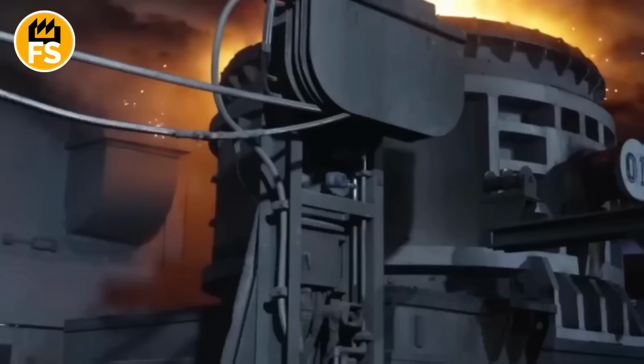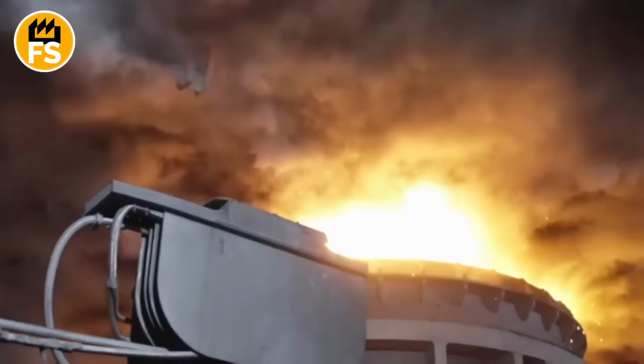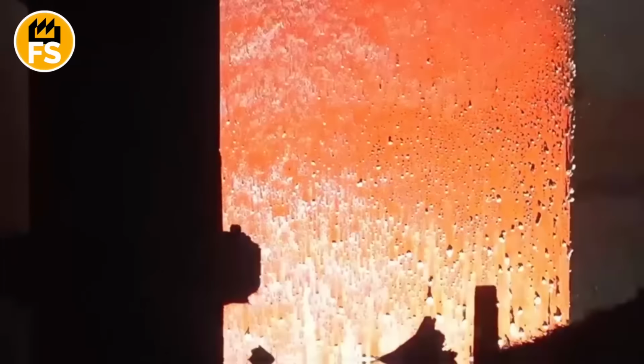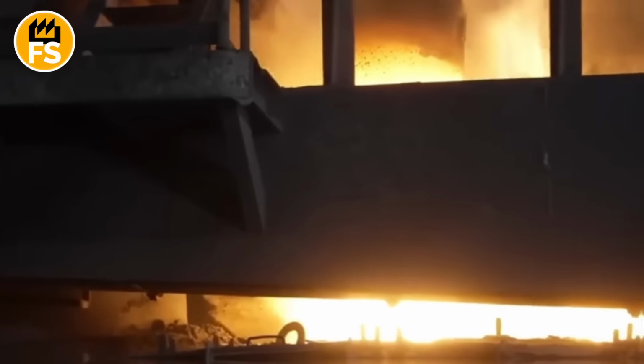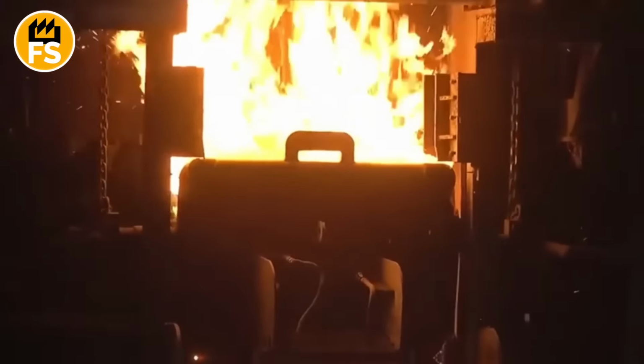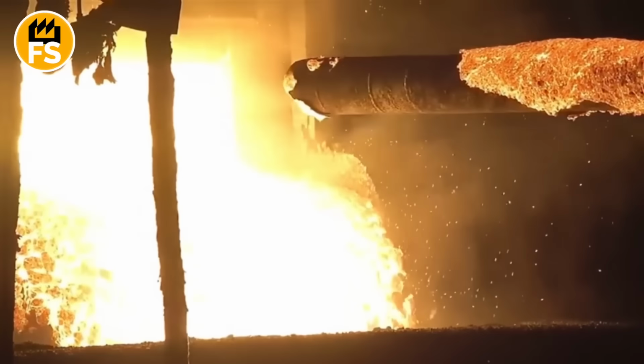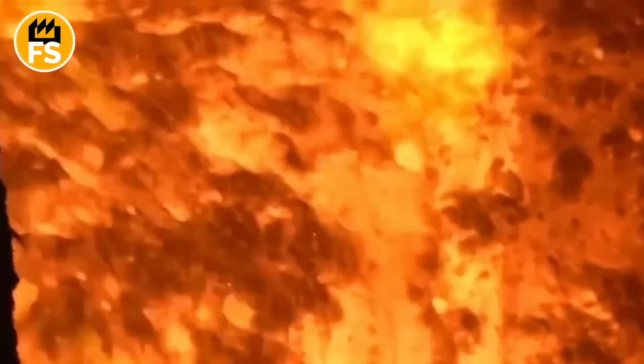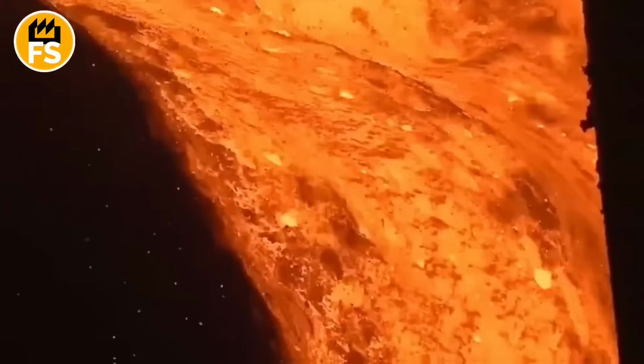After loading, the electrodes lower until they make contact with or get close to the scrap, and current flows through them. An electric arc forms between the electrodes and the charge, reaching temperatures up to 6,300 degrees Fahrenheit. Heating the charge under the arc's influence causes the scrap metal to melt rapidly. The molten steel forms a pool of liquid metal that mixes intensively thanks to electrodynamic vibrations and natural convection. This ensures uniform heating and metal composition. To purify the molten steel from unwanted impurities, oxygen is introduced into the furnace through special tuyeres. The oxygen oxidizes carbon, sulfur, phosphorus, and other harmful elements, forming slag that's easily removed.